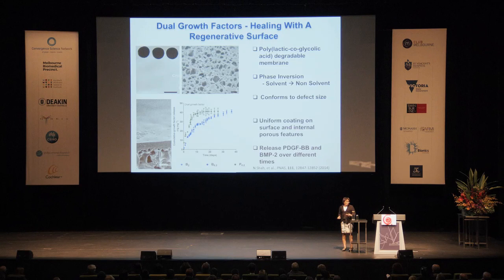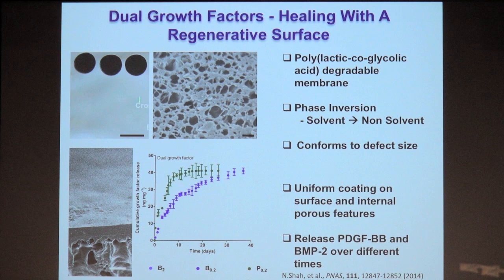The reason we introduce these growth factors in this order is because we want to be able to generate a vascular bed and then generate bone around the vascular bed. But to understand whether or not PDGF was important, we also did experiments with just the BMP2. Just forming the bone alone. So this is the foamy material with our layer-by-layer film on top. This is the rapid release of the PDGF on top, which is going to take place over 7 days, and the BMP2, which takes place over about a month.